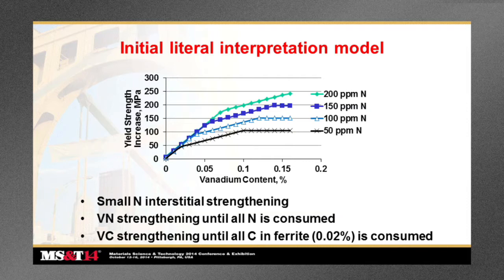Using that regression work, you can have this initial literal interpretation of what it's trying to tell you. What do we know for sure? That there is a relatively small contribution to the nitrogen interstitial strengthening, which would be the separation of the first straight lines, as you see right here. Interstitial nitrogen would separate those lines, that is, the higher nitrogen containing line would have a higher starting strength with 0 vanadium compared to the lower nitrogen levels. There may be more increment than what this graph shows,